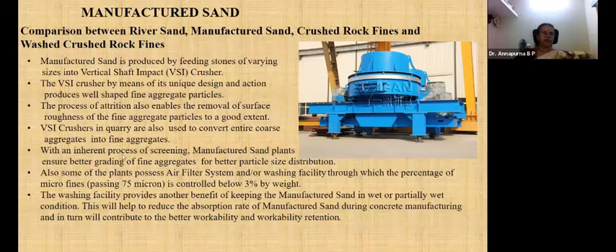With an inherent process of screening, manufactured sand plants provide better grading of fine aggregates for better particle size distribution. Also, some of the plants possess an air filter system or washing facility through which the percentage of material below 75 micron is washed off and controlled below 3% by weight. So the 75 micron fines are less than 3% by weight.